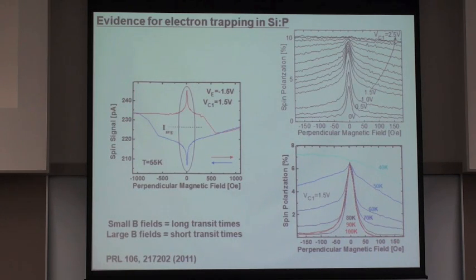So we're injecting spin that lies in the device plane, and we're detecting spin that lies in the device plane, but we're applying a perpendicular magnetic field. And so, as I showed you previously, our interpretation of our measurements is that what we're really measuring is the Fourier transform of the arrival time distribution. Now, you guys, I'm sure, know that there's this reciprocal relationship with a Fourier transform, so that the magnetic field scale of features that we measure is inversely proportional to the time scales that cause them. Just like I showed you previously, the oscillations in the spin precession get much larger when the transit time gets smaller. Likewise, the envelope of these cosine-like oscillations gets wider as the uncertainty in the distribution gets smaller. So when we make measurements on these phosphorus-doped silicon transport devices, we see data that looks like this.